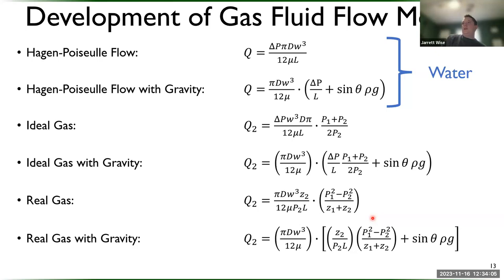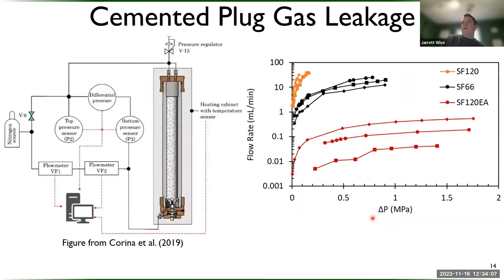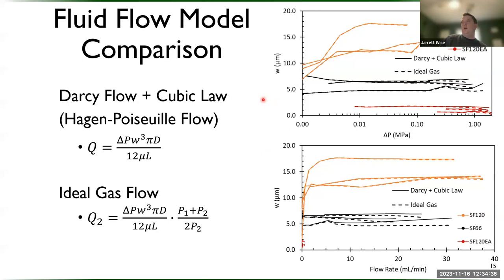These are purely theoretical models, but we wanted to compare them with what we're seeing in the lab. One of our collaborators over in Norway did small scale experiments in which they basically cemented a pipe, so cement casing shut, applied a gas pressure to the top of it, and measured the flow at the bottom, and measured the different flow rates and pressures for different cement mixtures they had. So we were able to get their data, apply our fluid flow models, and compare it with the water models to see how these really line up.